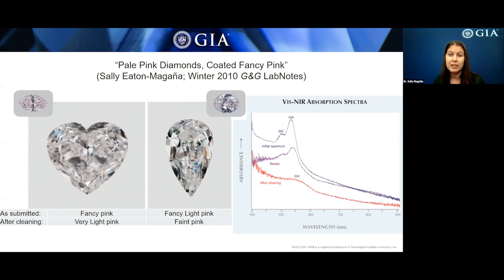Pink diamonds generally show a broad band centered at 550 nanometers. Instead, the spectra of both these diamonds displayed peaks centered at 505 and 540 nanometers. Additional submersion in liquid nitrogen led to a weakening of those peaks, and we subsequently fully cleaned the diamonds. The cleaned diamonds now showed the expected absorption spectra. When these were color graded a second time, we saw a decrease of several color grades for both. The treatment, we surmised, was likely meant to intensify the color of these pale pink diamonds, likely with the knowledge that the coating would not be permanent, but also perhaps hope that the coating would persist through the grading process.